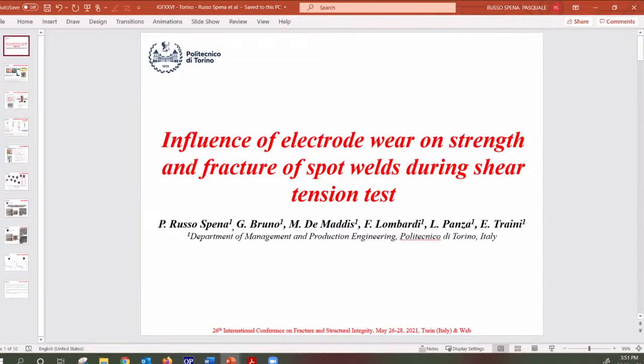We have examined the weld strength by using SORPAS software. SORPAS is a software devoted to spot welding. At the moment, I cannot show you the results, but basically the software is able to demonstrate that there is a certain coherency with the electrode wear that we simulated by building up the electrode inside the software simulator, because it can consider wear only by changing manually in the software the shape of the electrodes. At the moment, we have some promising results, but we need to match the welding signal better with the numerical simulation, because at the moment there is not a proper matching between them.